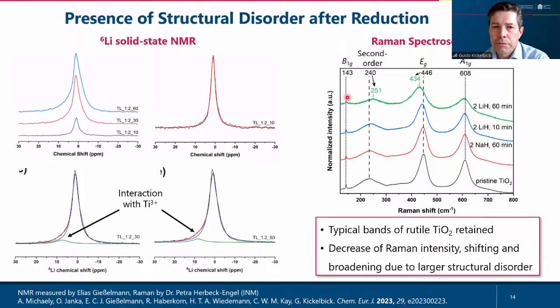If you look at the 6Li solid state NMR, a broadening of the peaks in the lithium NMR usually gives you information about the environment of the lithium in the lattice. You can deconvolute the experimental signals, and then you can see that you have a major peak for the usual environment, but this is quite broad already. So this tells you something about amorphization, or that not all lithium sites are occupied. In addition, we see this small peak in the deconvolution, and this is the interaction with titanium 3+. So this gives us some additional information about the species which are formed.